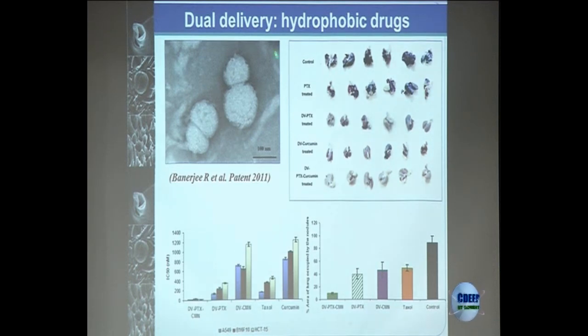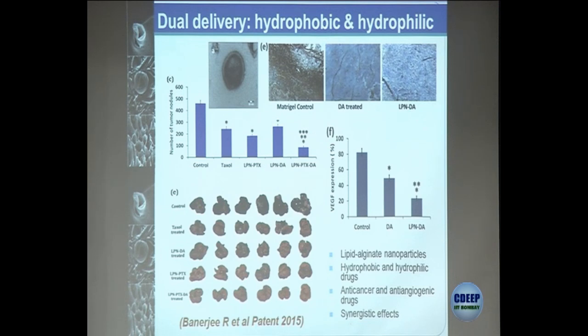Once again, these are the tumor loaded lungs. This is the conventional treatment by intravenous route, and this is just aerosols of paclitaxel and curcumin, which can clear up these tumors. What if you have 2 drugs, one hydrophobic and one hydrophilic? So this is the platform where you have a core shell particle. The shell is hydrophobic, which is the lipid based, and the core is a biopolymer alginate. And this can then deliver 2 drugs, one which is attacking the blood vessels associated with the tumor. That's referred to as anti-angiogenic, which means that you're cutting off first the nutrient supply to that tumor, and then you're delivering the drug which is killing the cancer cells. Once again, shown to be several-fold improvement over conventional therapy and has been patented.